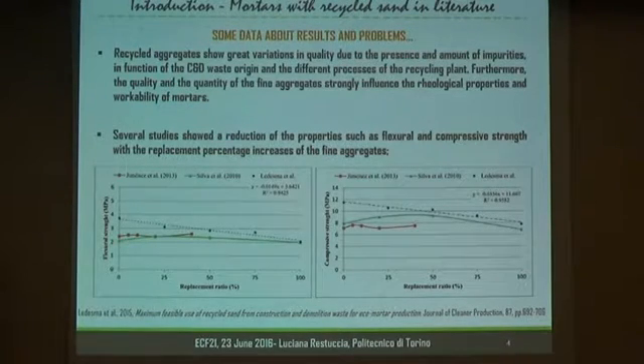In general, we found little literature about the fine fraction of construction and demolition waste, and we found that there are almost the same problems. For example, in several studies, we found a reduction of properties such as flexural and compressive strength with an increase of replacement of recycled sand. Furthermore, there is a very big problem related to the workability of the mortars. In fact, the quality and the quantity of the finer aggregates strongly influence the rheological properties of the mortars.